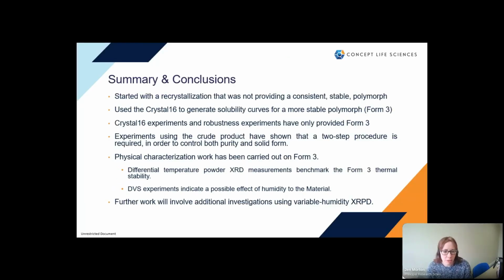Okay, so just our final conclusions to wrap up. We started with a recrystallization that was not providing a consistent, stable polymorph. We used the Crystal16 to generate solubility curves for a more stable polymorph, and the Crystal16 experiments and the subsequent robustness experiments that we did have only provided form 3.